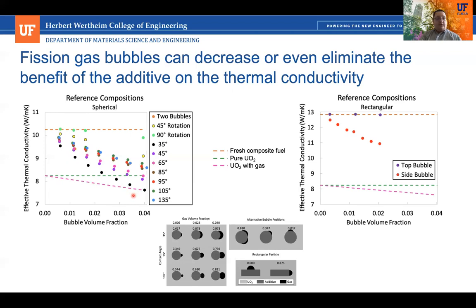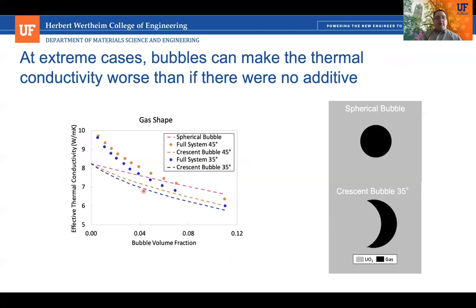Now that's significant, right? So this is worst case, obviously. In other cases, it has very little effect, but worst case, we can have a very large effect. So we wanted to look at that even further. So we went to larger bubble volume fractions just for these 35-degree and 45-degree contact angles when the bubble's in the direction of heat transport, so sort of the worst cases. And it gets even worse. We get down to the point where we've eliminated any benefit of the additive, but then it even gets worse than as if there had been no additive in the first place.